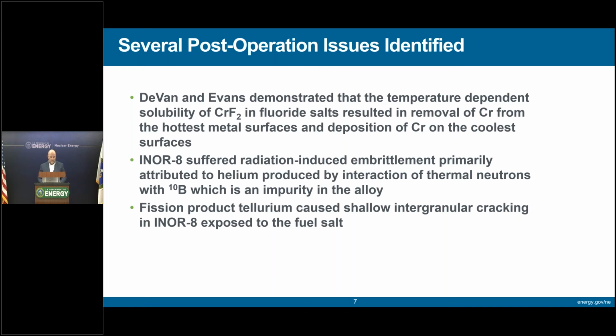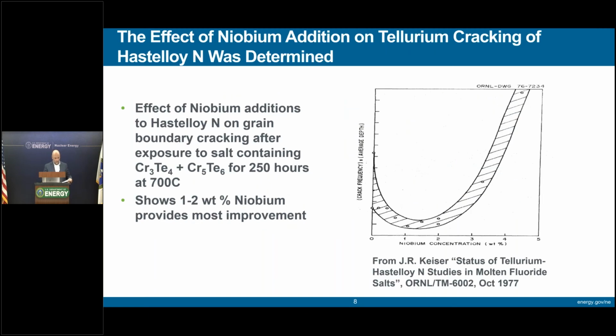Additionally, we have this other material, INOR-8, which suffered irradiation-induced embrittlement primarily attributed to helium produced by interactions of thermal neutrons with boron-10, which is an impurity in the alloy. Fission product tellurium causes shallow intergranular cracking for INOR-8 exposed to the fuel salt.